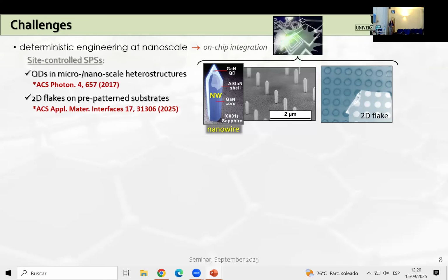So one way to achieve such site-controlled emitters is, for example, by including quantum dots into micro or nanoscale heterostructures, like, for example, nanowires, as you can see here. Or with 2D materials, we can use exfoliated flakes and place them on pre-patterned substrates, in which case we can achieve strain-engineered positioning of quantum emitters at specific locations.